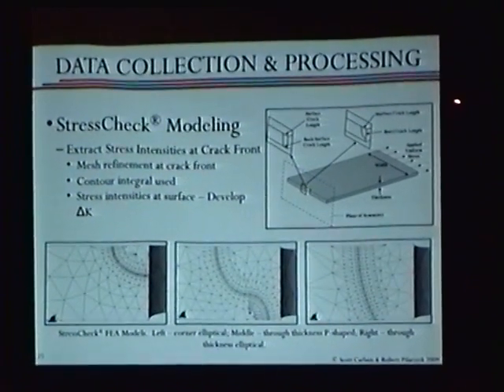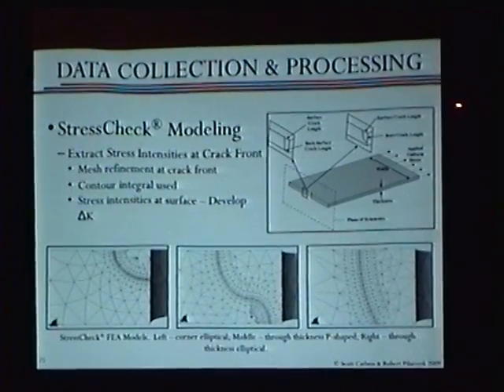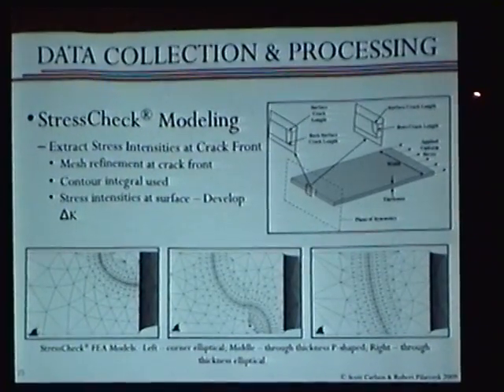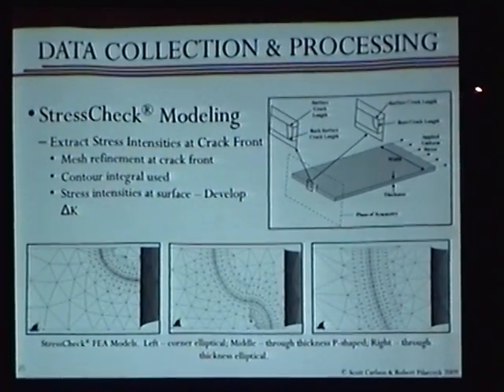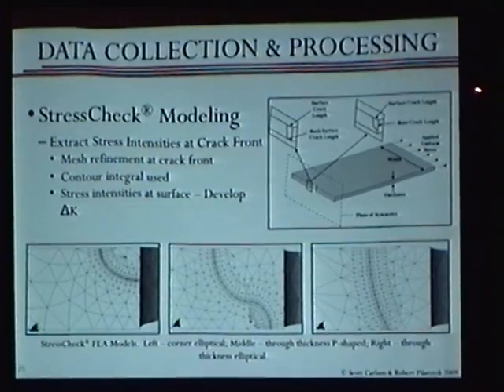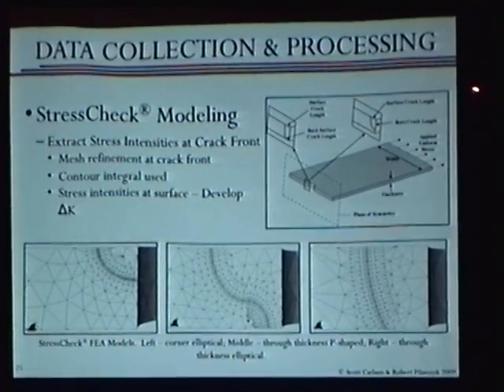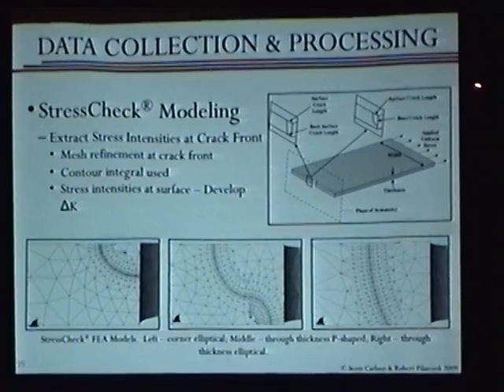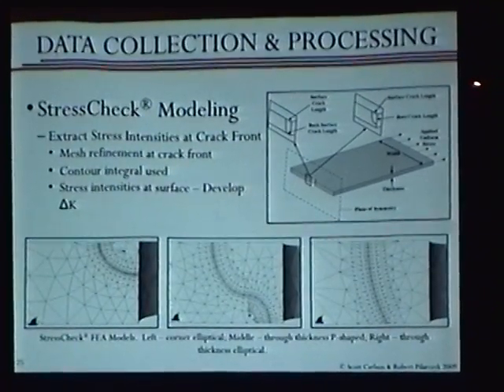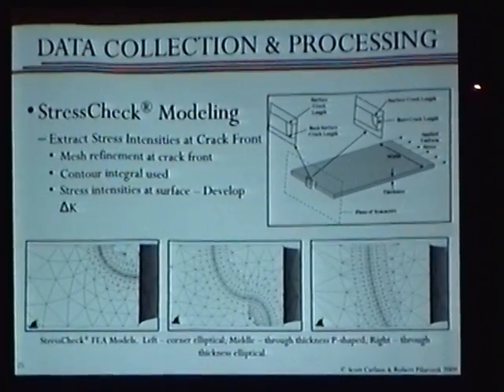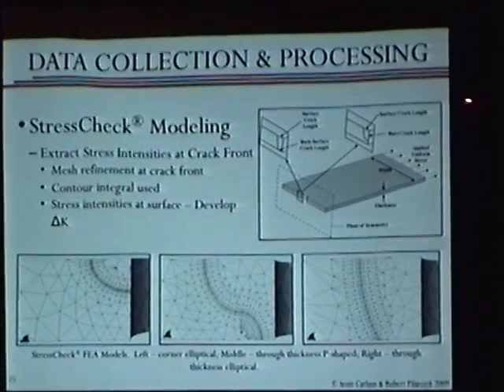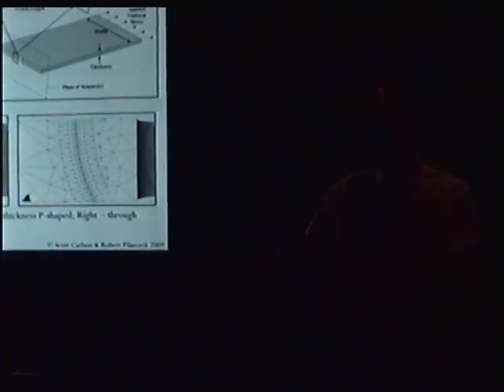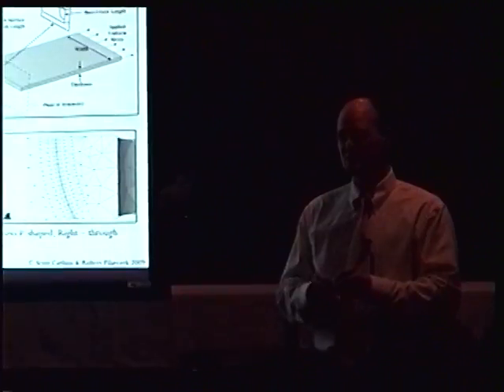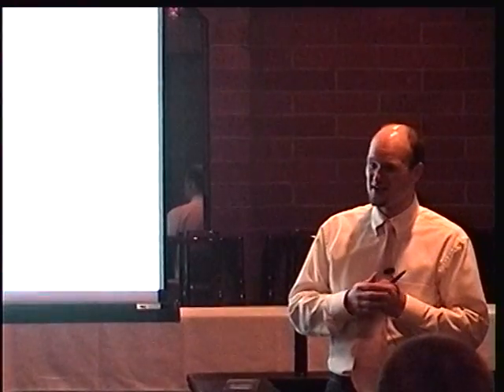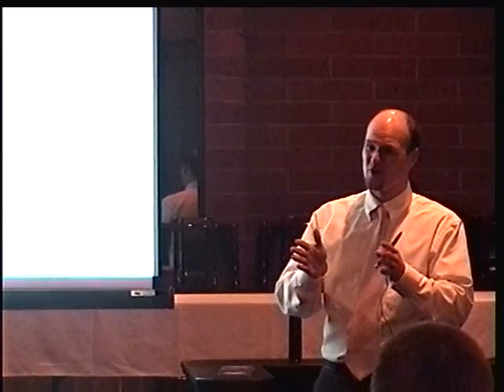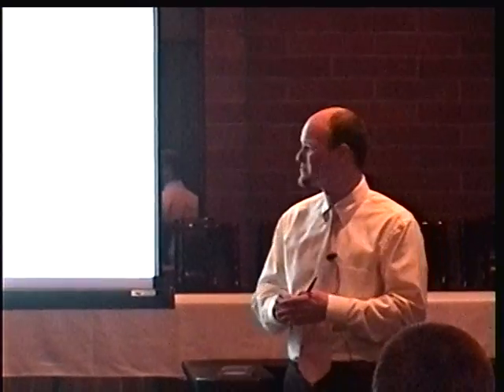So we understood that. We did some marker banding. We looked at how the crack shape changes as the crack propagates through the component. We got that nailed down, and then we had to take that data and get to something useful. Scott talked about stress intensity, and that's the way we can compare the two on an even baseline: look at a standard specimen and a cold worked specimen, and really relate the two and see what the difference is from this process. Can we figure out what advantage I'm getting from this process?